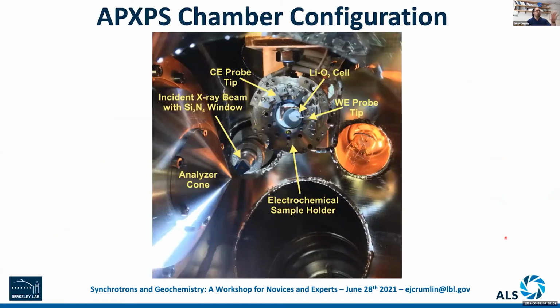And so for this first example, what I want to show is what it looks like inside one of these ambient pressure XPS chambers. It's a large chamber. This whole volume will be filled with the gas that we're interested in exposing to our sample. We see here a sample on a holder. This particular one is set up for an electrochemical system at a solid-gas interface, so we can even provide electrical stimulus to the sample. We have an X-ray transparent window, so X-rays can come through but the pressure gradient is held. And then right through here is the analyzer cone, where there's a very small aperture where the gas is coming through, but also, most importantly, the photoelectrons that are being excited. As the sample is moved into place, it gets in line with the X-rays and the analyzer.